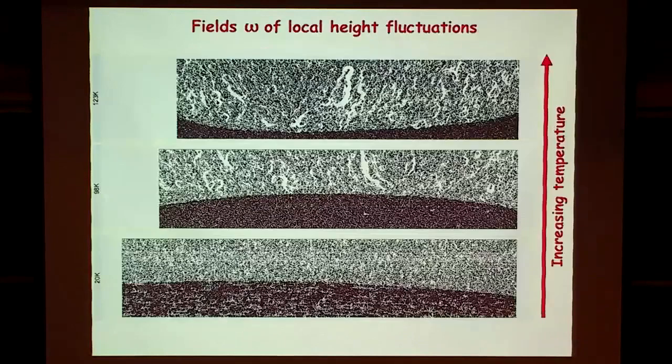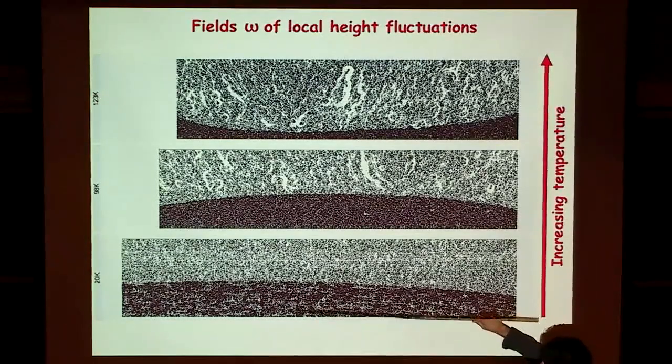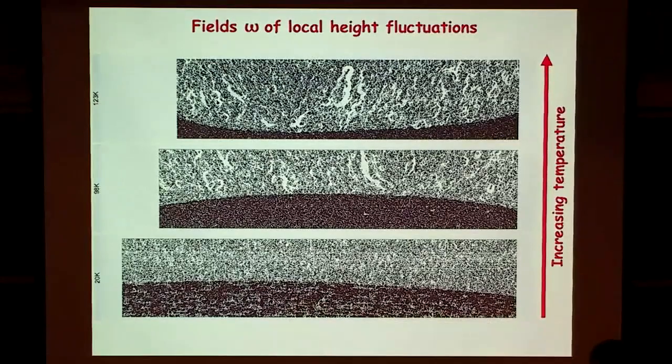For creep and for fatigue, I didn't do so much, but I have some. We can already see some interesting features. These black parts are fatigue pre-cracks, and we clearly see lines that probably correspond to cycles. So there are probably a lot of interesting things to do with this way of analyzing fracture surfaces to get insight into fatigue crack propagation, but these are really preliminary remarks.